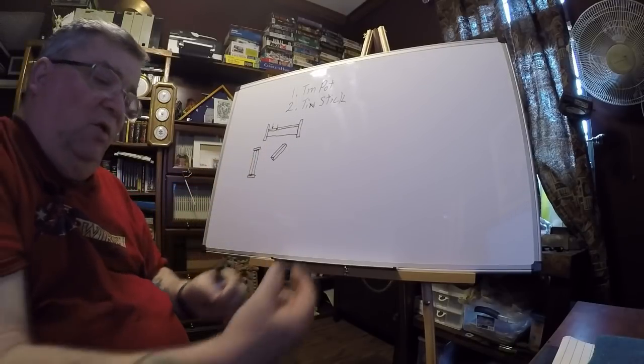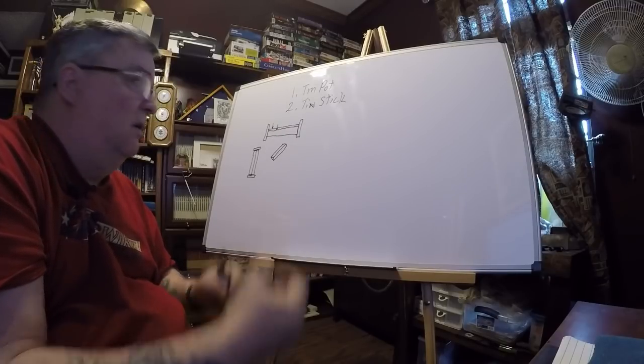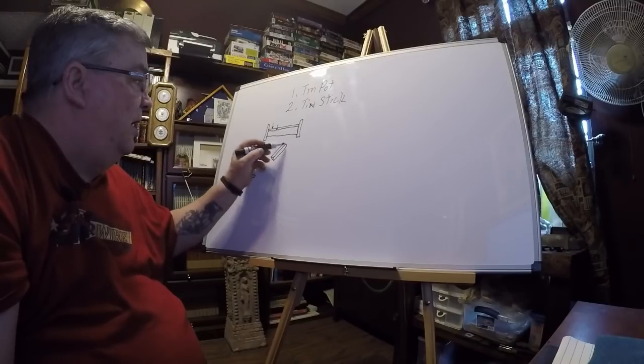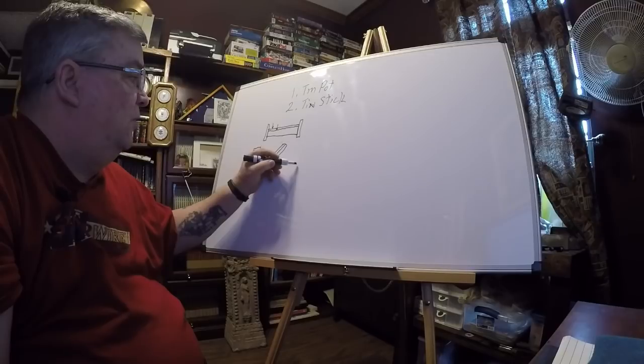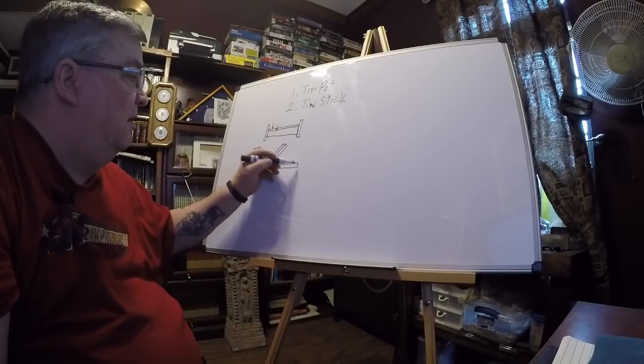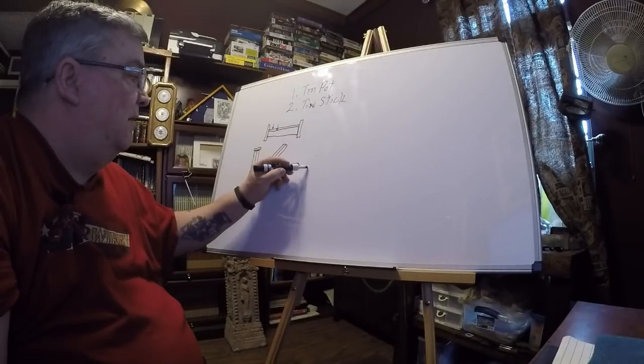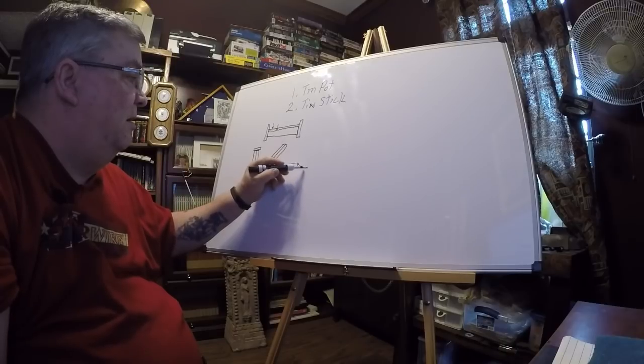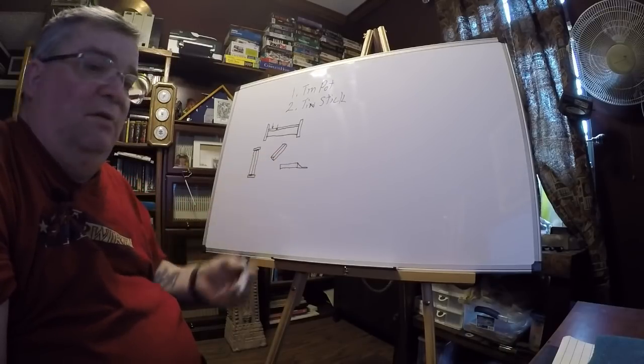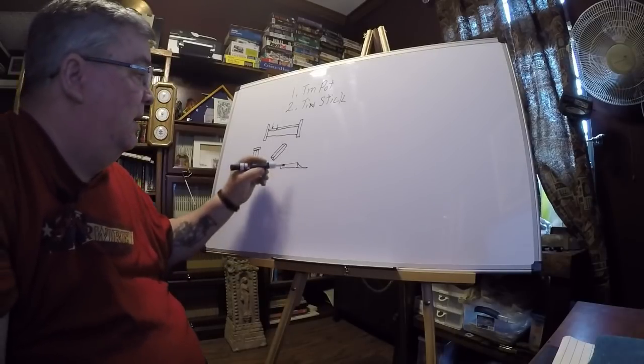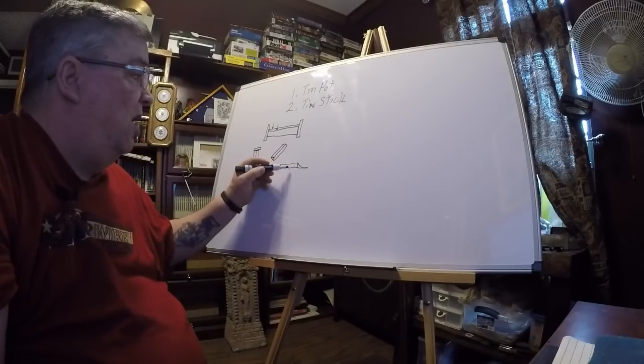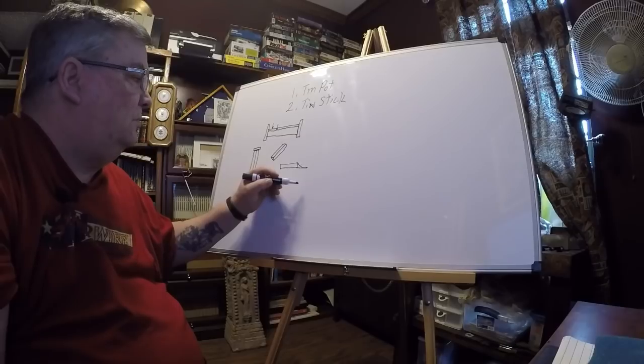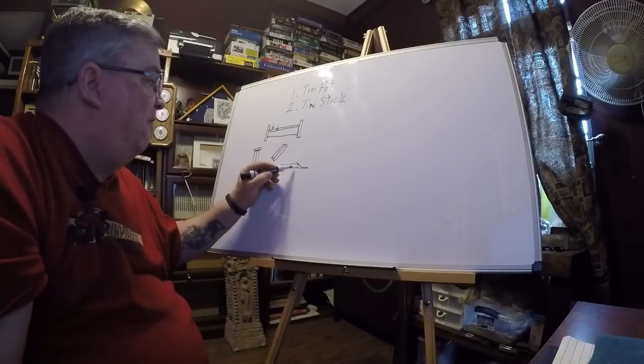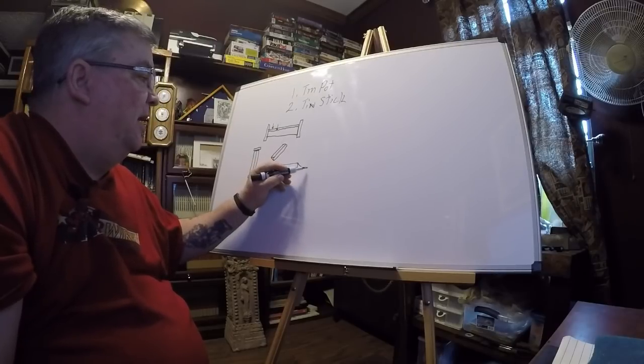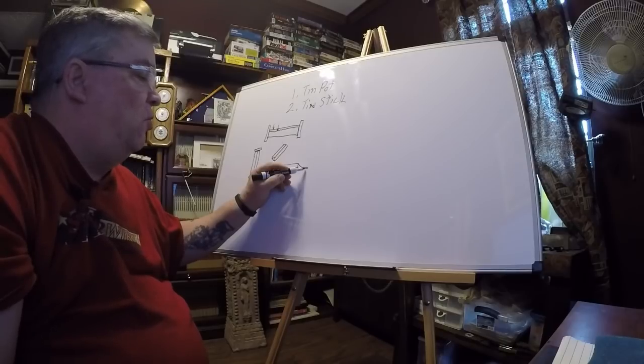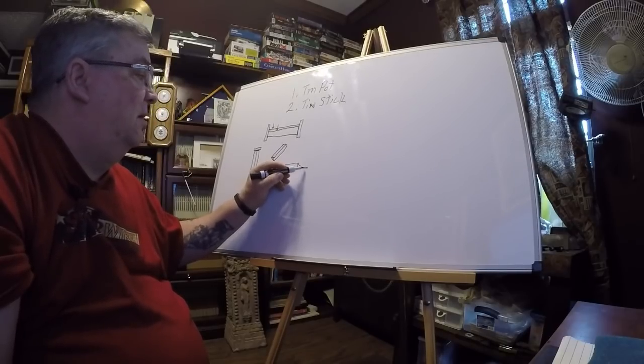Now, it's only going to be about so wide at its widest. You take that and hit it with a hammer on one end until you have something like this. You have the stick, and then you have some thin tin, thin enough, let's say, a piece of paper thin. If you've got to do a lot of them, you just continue to flatten this with a hammer and draw it out, so it's harder for this surface to melt than this surface, because the heat is absorbed more quickly here. So you just rub it.